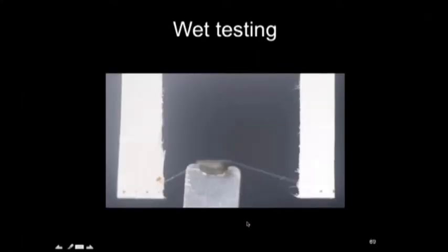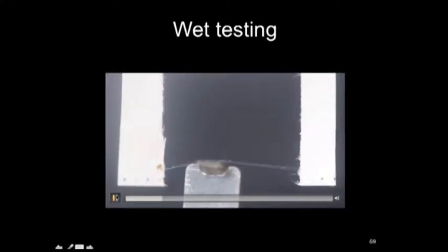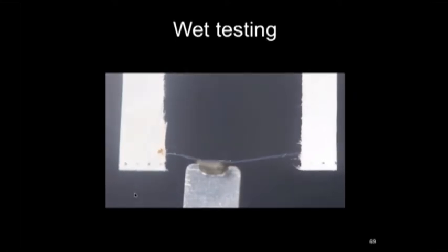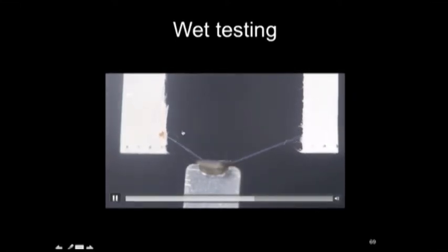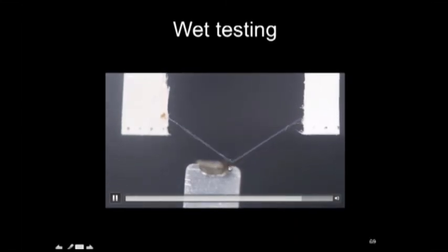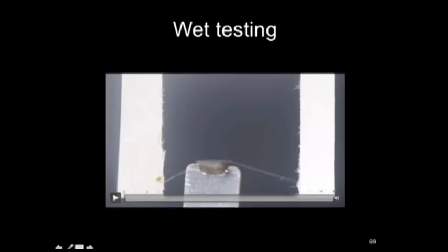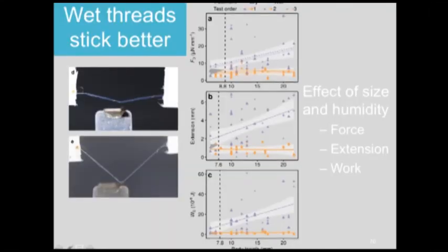And that's quite clearly demonstrated in our data. We see that both across size and between treatments, there's a clear difference between how the silks perform. Greater adhesive force is generated, with more extension of the overall fiber, leading to greater energy dissipation. Between tests, there was a slight difference. We tested these multiple times, so that the first, second, and third generally showed a decrease in performance. However, that was generally not different in anything except adhesive force.